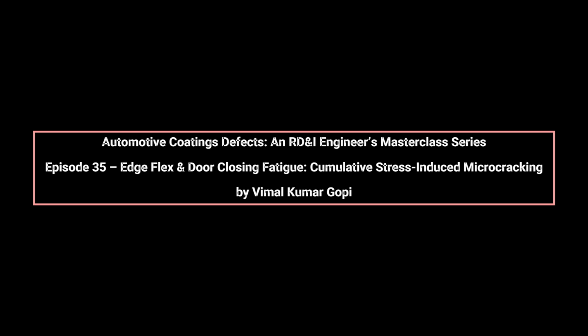Crosslink density plays a decisive role. Highly cross-linked coatings resist chemical attack and abrasion, but have limited elongation. When subjected to repeated flex, they accumulate fatigue damage rapidly. Lower cross-link density coatings tolerate deformation better, but may suffer from reduced hardness and long-term durability. OEM clearcoat and primer systems are carefully balanced to survive millions of microstrain cycles without catastrophic crack propagation.